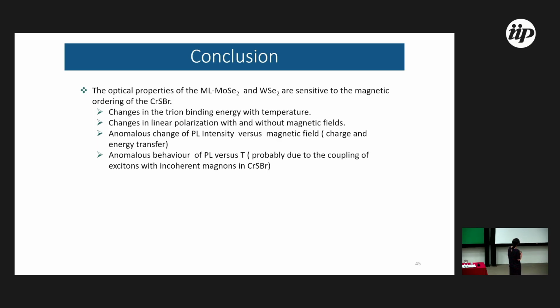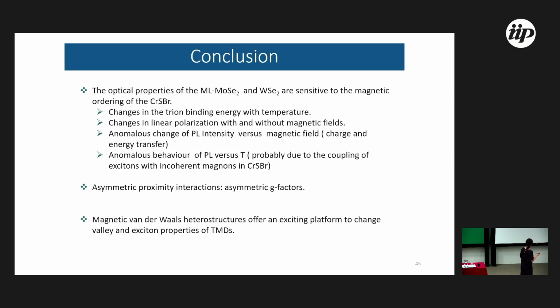So the conclusion is, there are a lot of surprises, and you can use this TMD to be a sensor of magnetic properties, for example, or you can use CrSBr to change valley and exciton properties of TMD. You can change trion binding energy, we can change linear polarization behavior, and you can observe anomalous change of PL intensity versus magnetic fields, and anomalous behavior of PL versus temperature. So there's a lot of things to discover. You can have an asymmetric proximity interaction. Of course, I do not understand everything. I have explanation for a lot of things, but I cannot go into detail. So there are other materials that can be combined with CrSBr, which can be interesting to modify properties. So it's engineering.